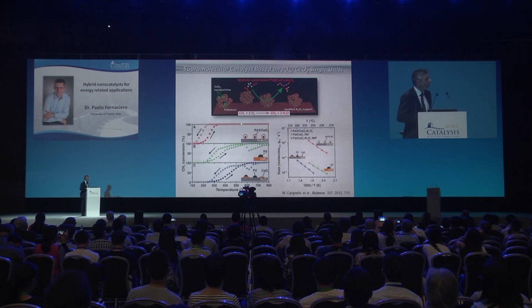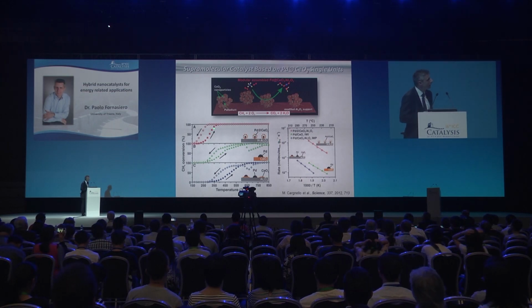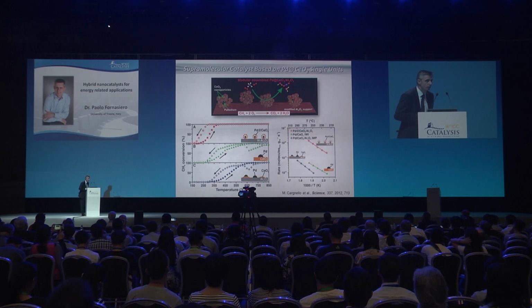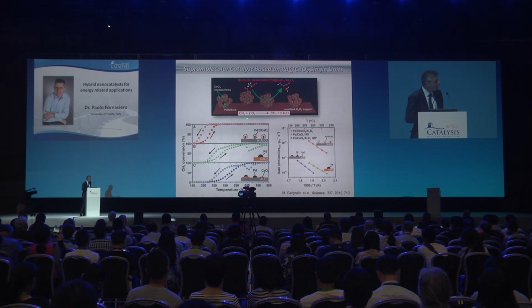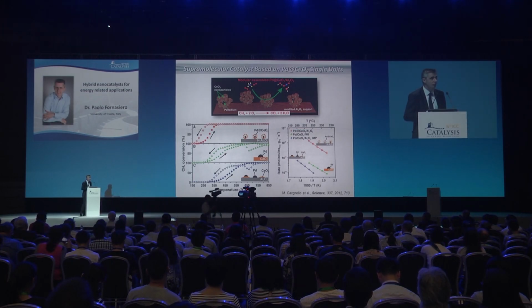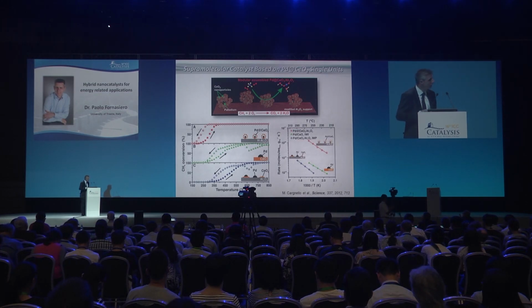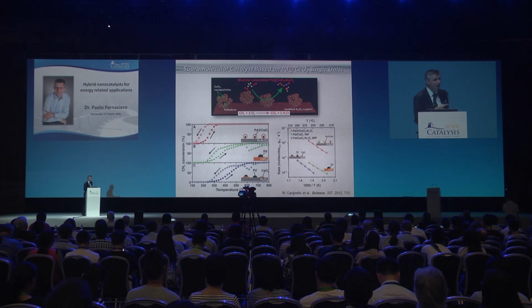But very importantly, not only can you activate methane at very low temperature, at high space velocity, so interesting for real application, but you do not observe this deactivation here at high temperature, which was related to palladium oxide to palladium metal decomposition, which means that CeO2 is really effective in giving lattice oxygen to palladium.